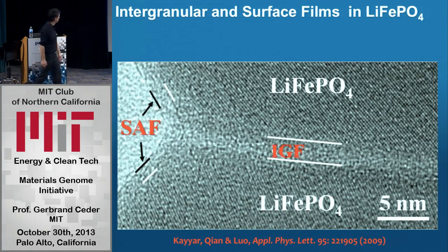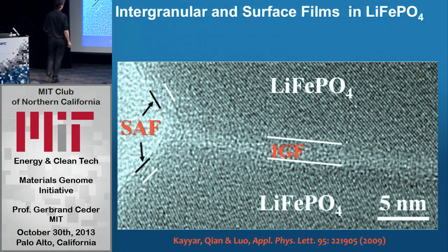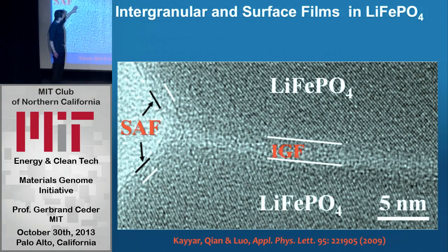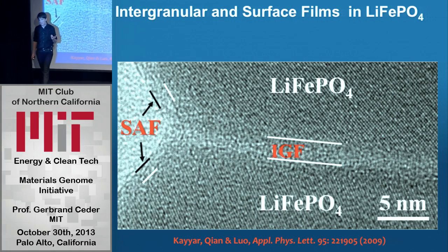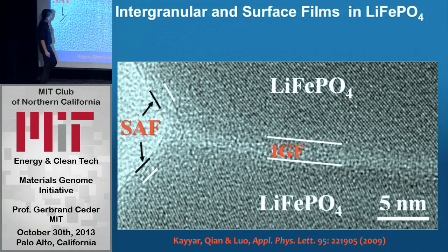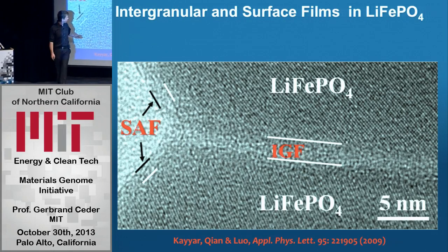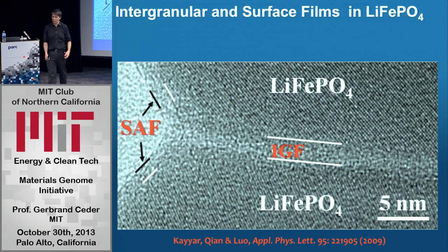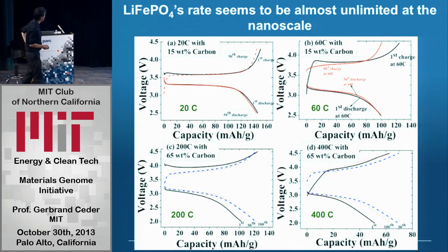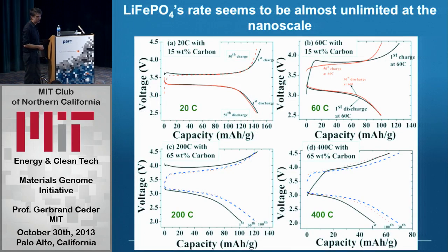And you actually see this here. This is a TEM picture. This is lithium iron phosphate, and this is the intergranular film, which is the fast ion conductor. So you have pathways for fast lithium-ion diffusion along the grain contacts, and then it can go rapidly into the grain. And so we established what was, at the time, the highest charge and discharge rate for any electrode material.